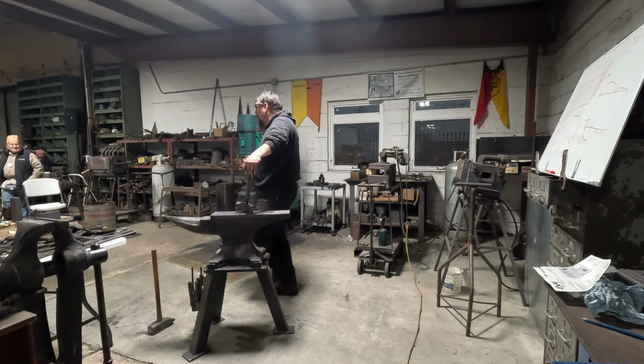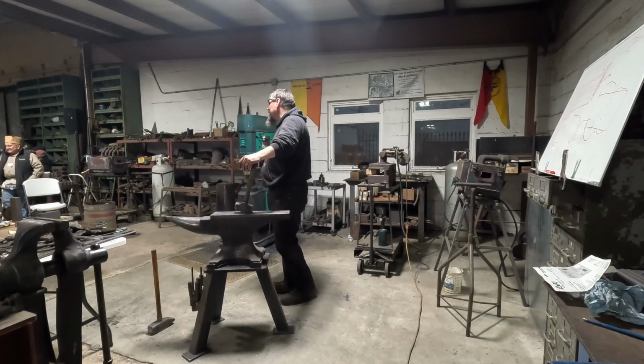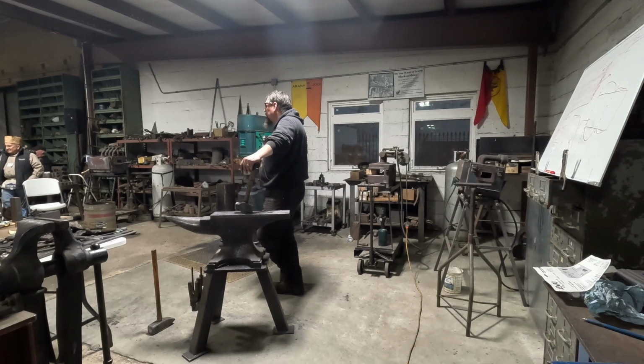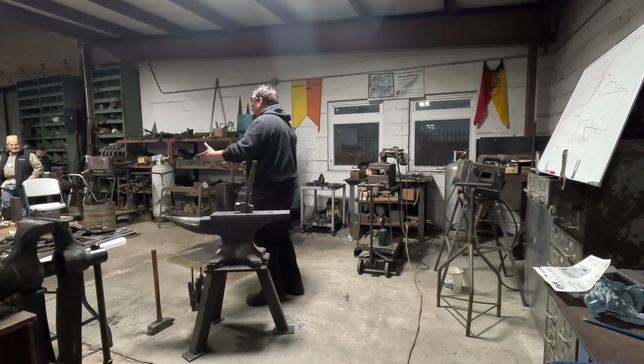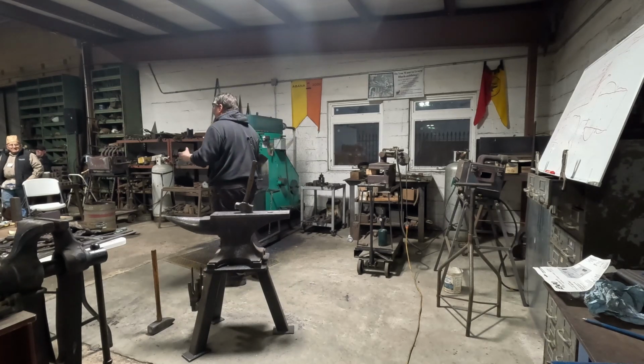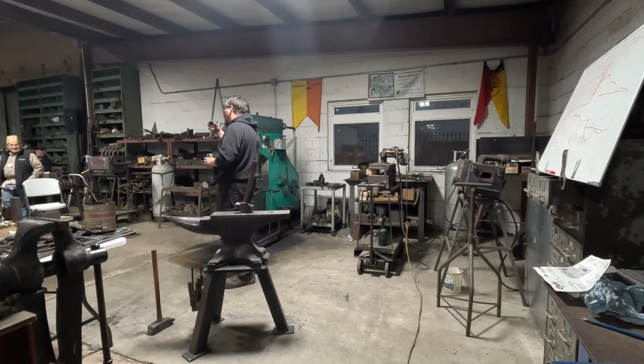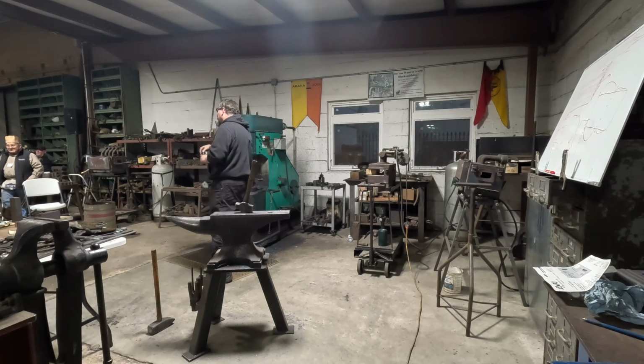Are you thinking that you've got bronze of the same composition, if they're working in really different ways? When you think of hot short steel, it's soft. Ah, okay. So in the case of the hot short steel, what you're forming is a new compound that's outlining grain boundaries, and that compound has a lower melting temperature than the underlying material. So iron sulfide coats the grain boundaries. Iron sulfide melts at like 1730, and we want to forge at 2300 or 2400 F. And so now you've got liquid at your grain boundaries, even though the underlying steel is still solid. When you hit it, it falls apart. It's the same idea. Yeah, the copper in the steel does the same thing.